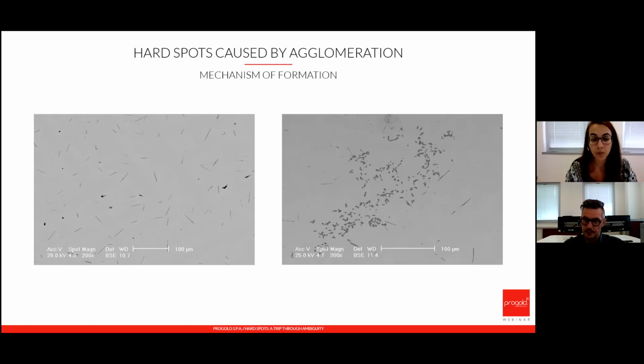And as I said before, when we have an alloy, we have to respect certain ratios in order not to have undesired reactions. So if we use an alloy that has been used many times and we're enriching it in certain elements, at some point these elements might react with each other. Initially, we are going to see what is happening on our left, these needle-like shapes that do not give a lot of problems. But if we keep on reusing this, the needle-shaped forms are going to enlarge themselves and they're going to become what we have in the right picture.